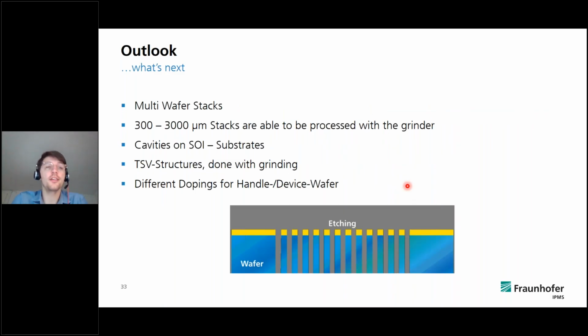What's next in this project, with the results that we got within this project, is doing multi-wafer stacks. So not only 2 silicon wafers bonded together, but actually 3 or 4, also divided by oxide, for example. We want to process not only the 1.5 millimeter thick stacks that we had so far, but we also want to increase the thickness of the stacks up to 3 millimeters and also down to 300 microns, because maybe if you remember, we were talking about stack thicknesses of almost 400 and a bit. And right now we try to go down to 300 as well, but that's not very high rated in the